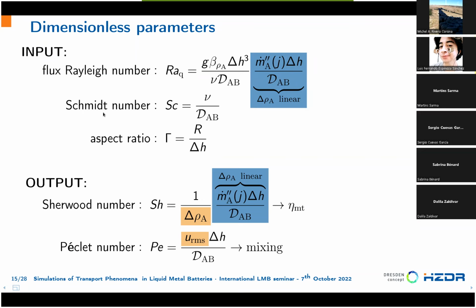The second important parameter is the Schmidt number, that contains the ratio of the momentum and mass transport diffusivities, and then as well the aspect ratio of the cell. What are the outputs? From the application, we are interested to know the mass transport overvoltage, so the concentration difference across the layer. And this can be cast inside this Sherwood number, that is at the end the ratio between the linear concentration difference and the actual one, measured from the simulation, or from the experiment if you do an experiment. And the second parameter of interest is for mixing, so it's the velocity. And in this case, we use the Peclet number as a relevant dimensionless parameter that contains the velocity in the layer.